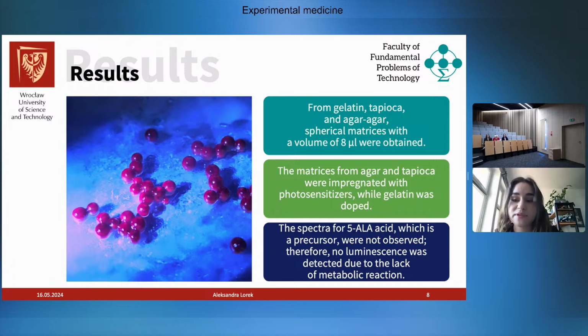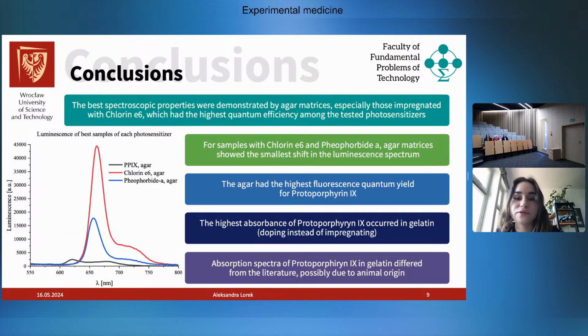This outcome was expected, as the conversion process typically requires cellular metabolism, which was not present in our in vitro setup. And the best spectroscopic properties were demonstrated by agar matrices, especially those impregnated with chlorin e6, which had the highest quantum efficiency among the tested photosensitizers, and gelatin influenced the expansion of the main band maxima for other photosensitizers.